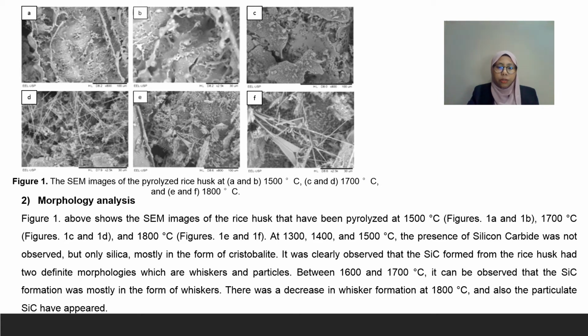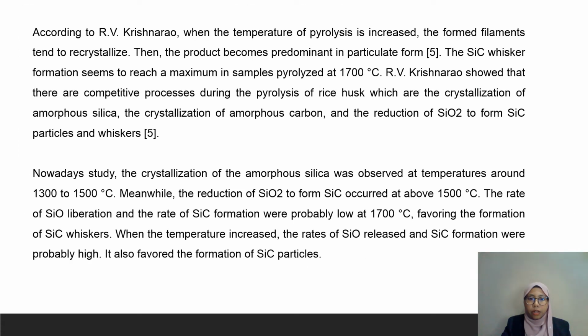Between 1600 and 1700 degrees Celsius, it can be observed that SiC formation was mostly in the form of whiskers. There was a decrease in whisker formation at 1800 degrees Celsius, and particulate SiC also appeared. According to R.V. Krishna Rao, when the temperature of pyrolysis is increased, the formed filaments tend to recrystallize. Then, the product becomes predominantly particulate. The SiC whisker formation seems to reach a maximum in samples pyrolyzed at 1700 degrees Celsius.